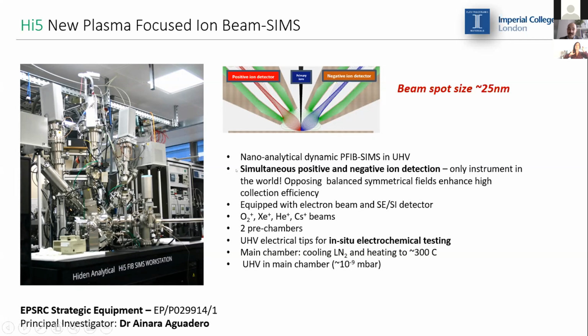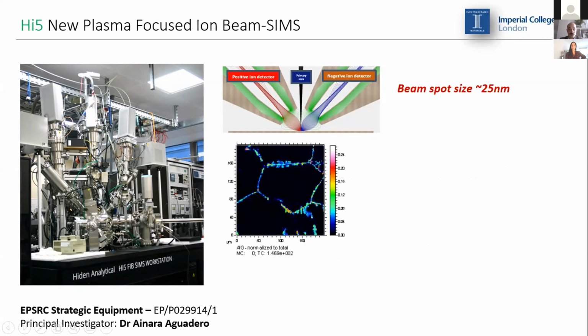Another unique thing is that it's got a simultaneous positive and negative ion detection. So we can analyze positive and negative ions on the exact same spot of the samples. So this actually will allow us to investigate even further, for instance, grain boundaries, and have a more detailed investigation on the chemical composition.